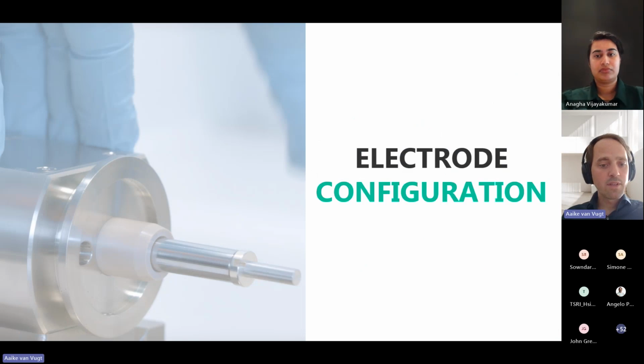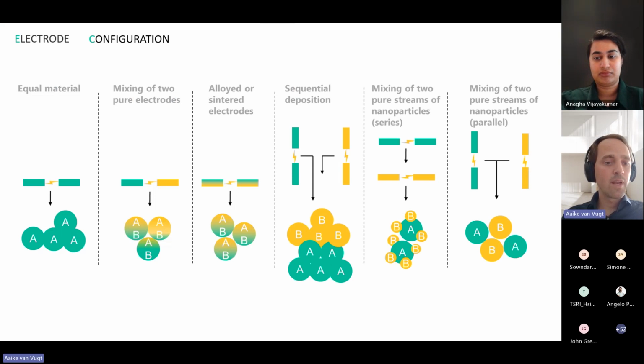The electrode configuration gives you a lot of capability to mix materials. So you can use 2 electrodes of the same material, so let's say silver and silver, then all particles are pure silver. If you have 1 electrode of silver and 1 of gold, then you will have particles of pure silver, particles of pure gold, and particles of anywhere in between. If you really want to control the stoichiometric mixture of the materials in each particle, you could use pre-alloyed electrodes. This could be pre-alloyed electrodes of binary, ternary, or any combination that you are interested in.